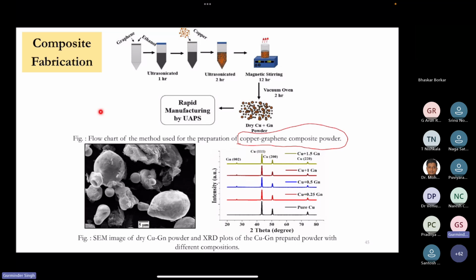The important thing is people were trying to use this copper spherical particle and mixing it with the graphene in a ball milling process. But you are damaging the spherical shape of the particle. We need a spherical shape, otherwise we will not be able to sinter it.